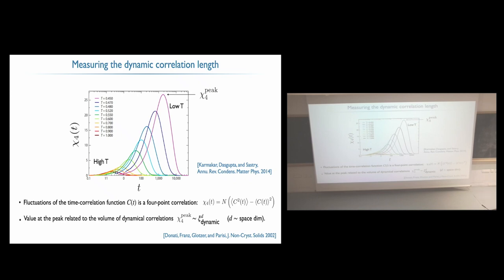So why 4 points? Well, C of t is already comparing the structure at 2 times, time 0 and time t. And when you look at these fluctuations, what comes out are basically 2 different points in space. So this is why we call this 4-point correlation. So this 4-point correlation as a function of time. Here, these are simulation results.